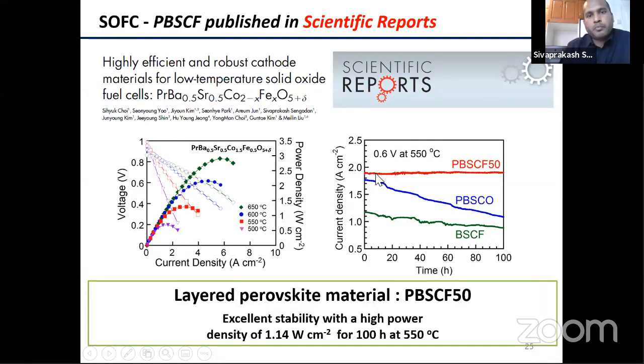Next we check the performance or stability of this material. This praseodymium, barium, strontium, cobalt, iron oxide shows very stable performance over 100 hours. Whereas without iron, it shows a sharp degradation.